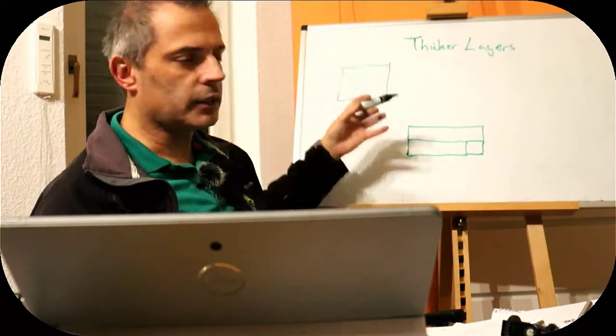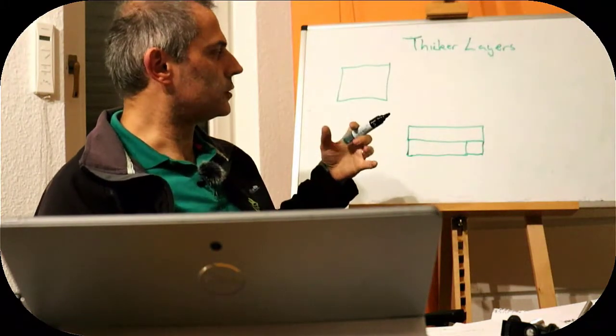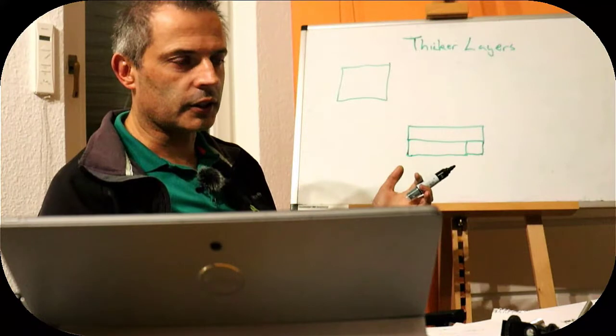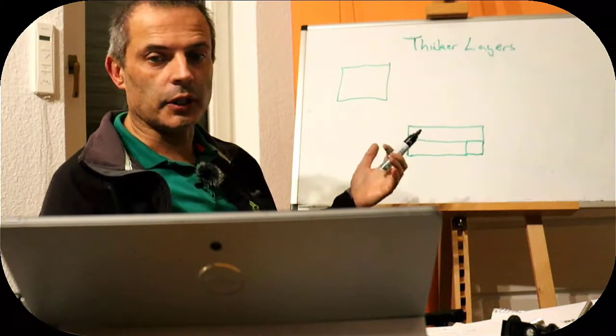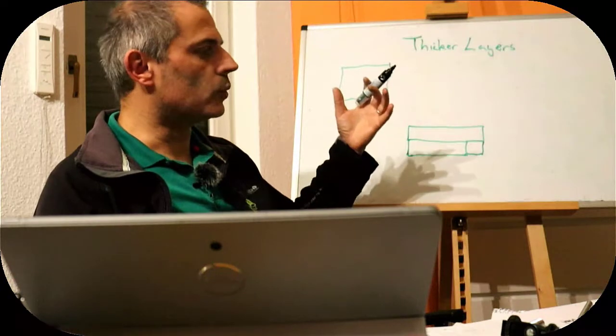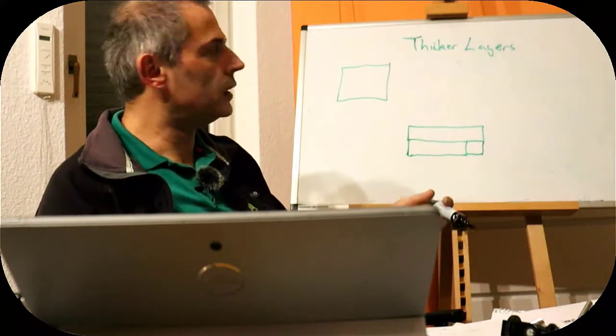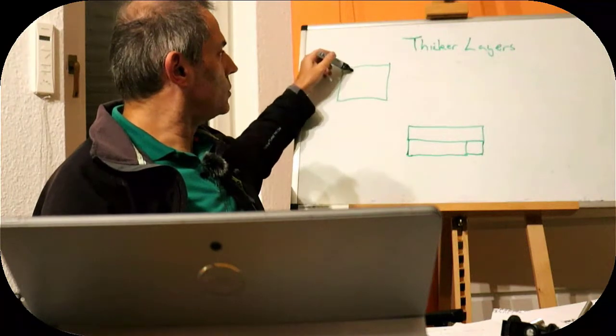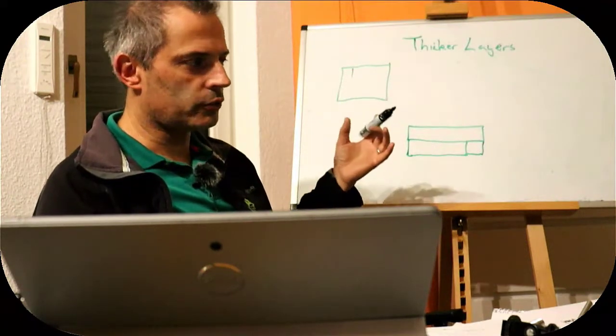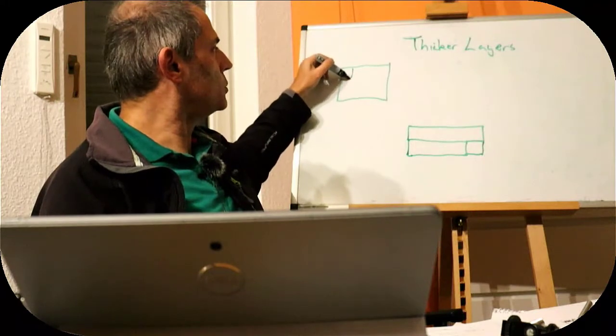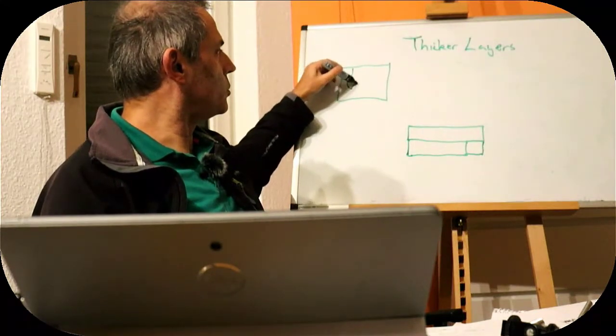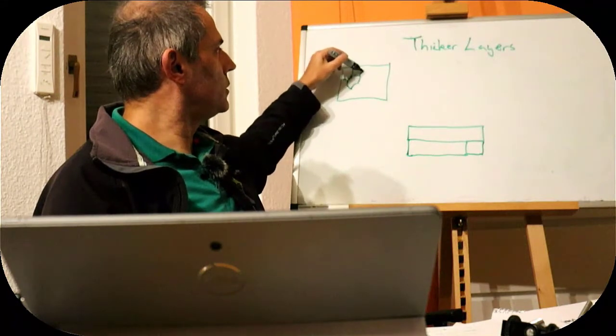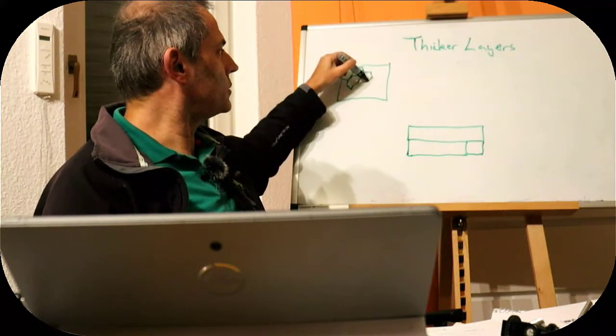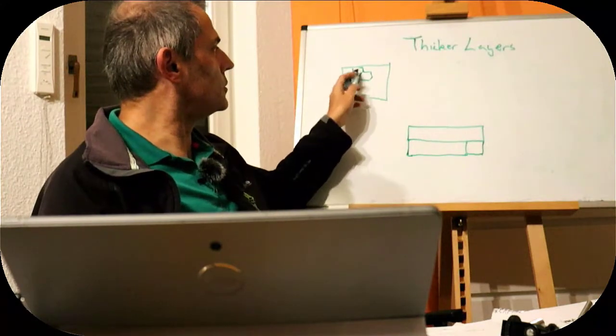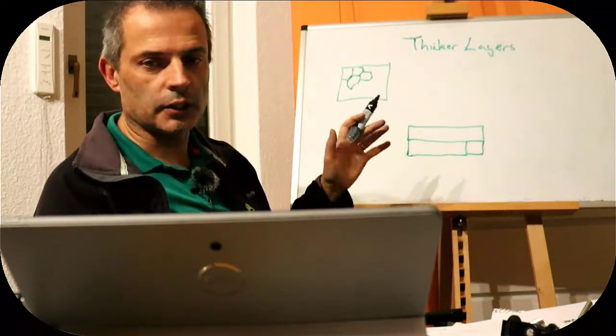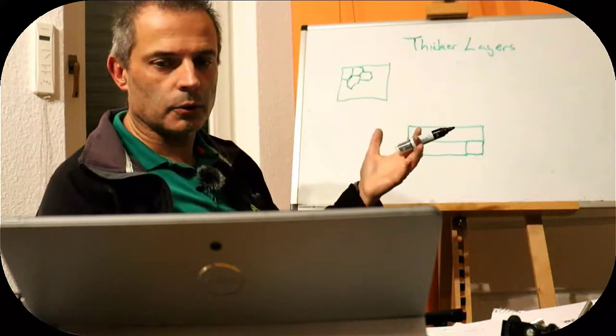if we make the surface smaller than the underlying thing, we can see that in many cases. So if we look at drying paint or a lake that has dried out, some mud, we will typically see, first of all, square cracks, and then they will modify themselves and become mostly hexagonal. So we'll end up with a hexagonal-ish pattern of stress cracks in the surface that go down, and if these hexagons are quite big, they will tend to peel up on the edges as well, because they will also start to shrink.